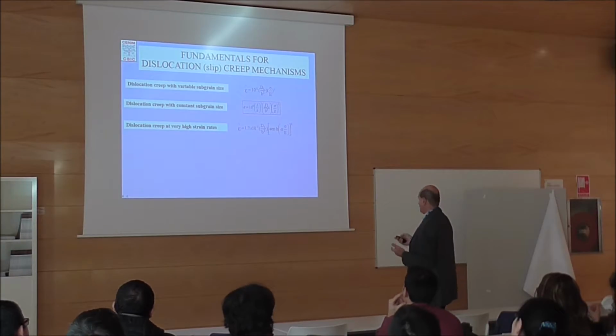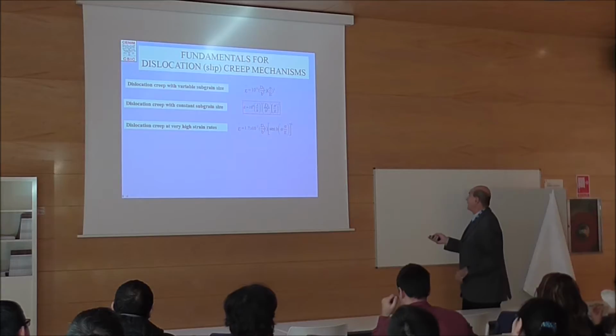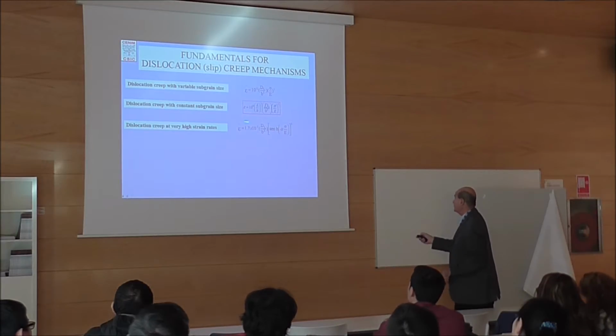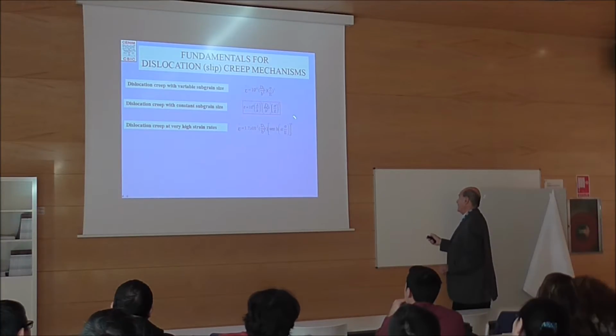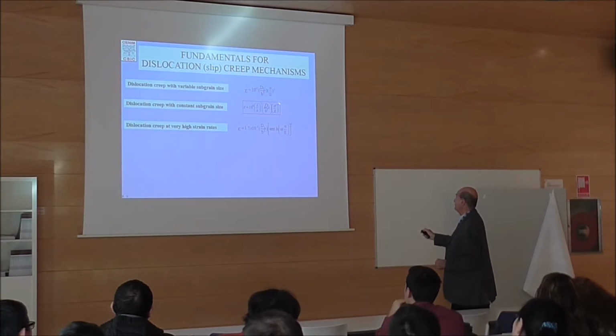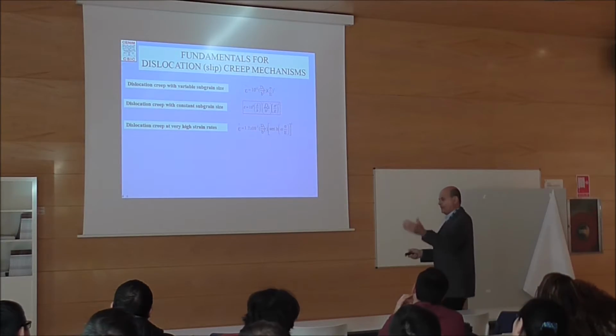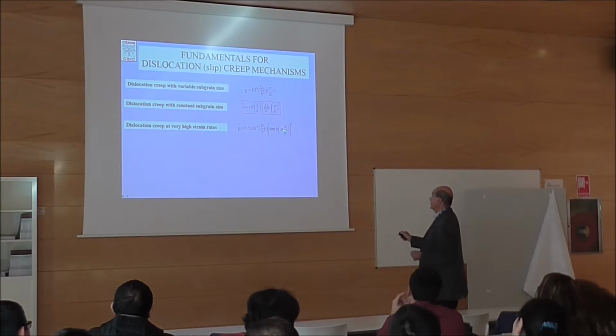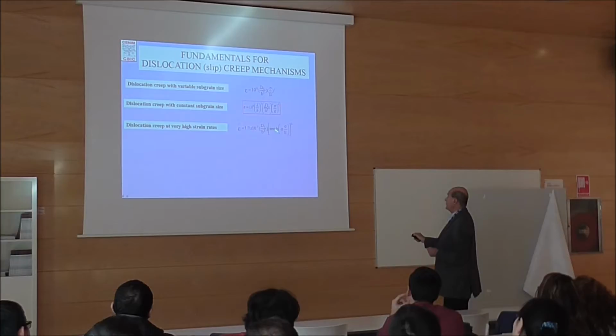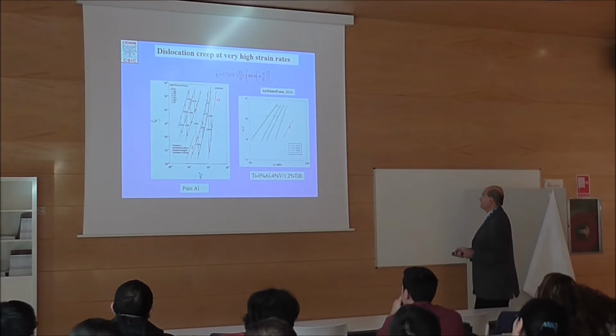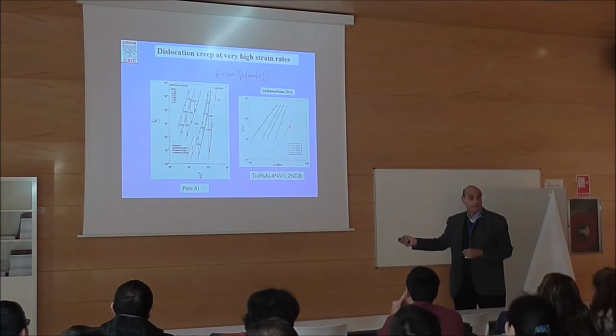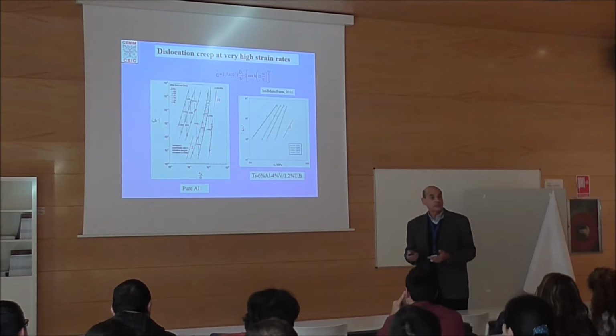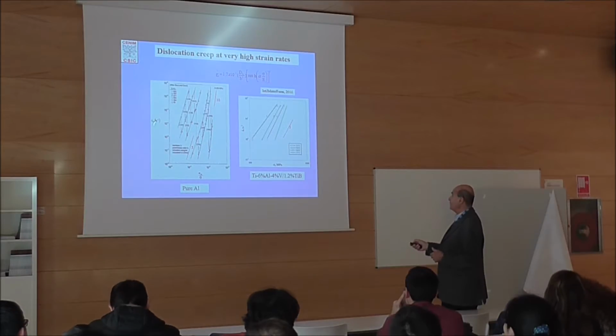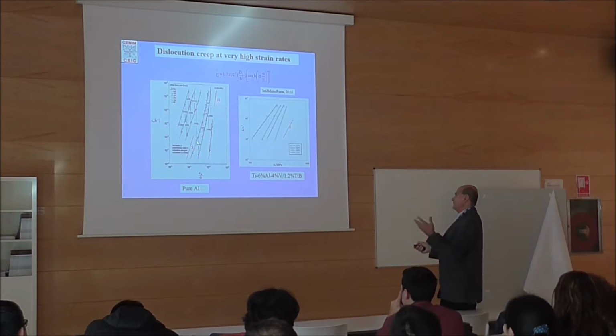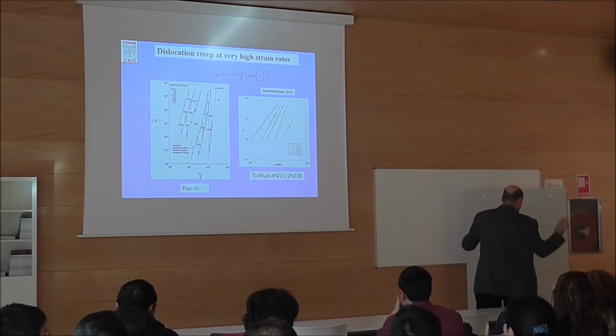And I'm going to go just very little on this equation because I have no time. And you see this is a hyperbolic sine equation with an n exponent that, okay, we don't care about now, probably is about 5, if we have some hypotheses. But in general, the important part is that we have an equation for slip creep, but with a hyperbolic sine. And for the hyperbolic sine, we have a demonstration of that. You take a material like this, a pure aluminum, and you test at a very high strain rate. If the temperature is not very high, what? I didn't do it.